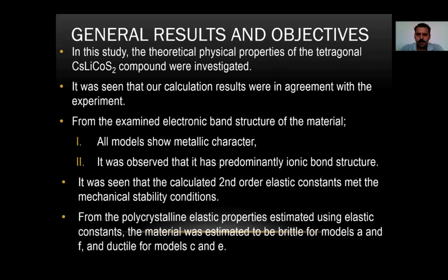Now I would like to talk about the general results and objectives of our study. In the study, the theoretical physical properties of the tetragonal title compound were investigated. It was seen that our calculation results were in agreement with the experiments. From the examined electronic structure of the material, all models show metallic character. It was observed that it has a predominantly ionic bond structure.